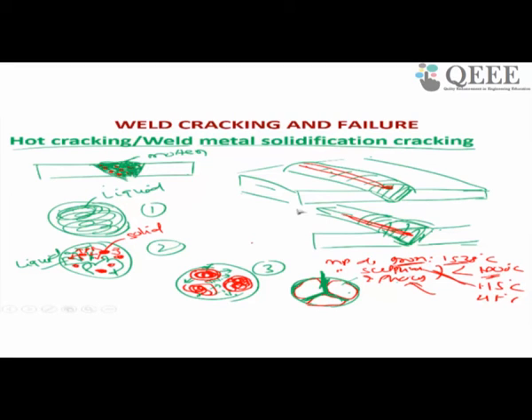Because of this liquefaction effect, you get a crack, and this is called a hot crack or solidification crack. The moment you do welding in the presence of low melting materials, you get this kind of crack. This crack mainly happens if your base material has different elements which have a large melting point difference.